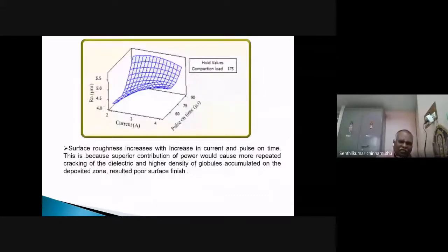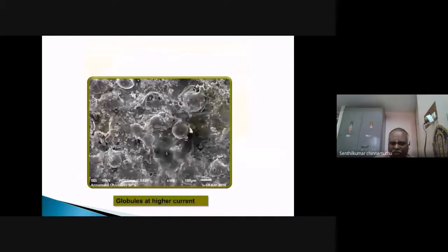And the surface roughness. In the case of surface roughness, the effect of current and pulse on time: if both current and pulse on time keep on increasing, the surface roughness increases because more amount of material is melted and deposited on the surface. Whereas at lower current and lower pulse on time, the material is deposited, but in the case of higher current and pulse on time, erosion takes place because of the cracking of dielectric. More repeated sparks crack the dielectric, and high density globules are formed or accumulated on the surface, resulting in poor surface roughness. See, globules occur at higher current. This is the globules which occur at a high current.